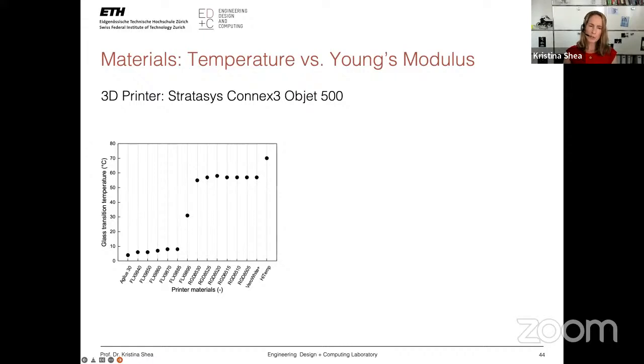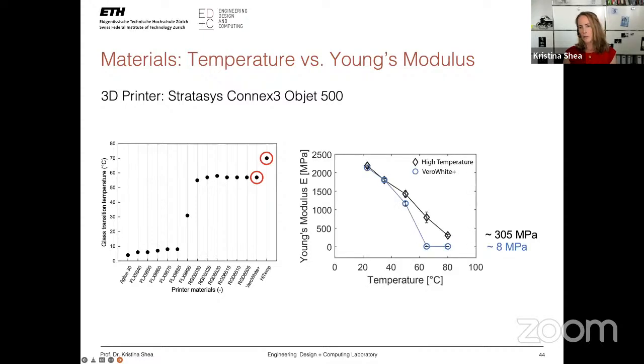And here the principle that we're going to use is a bit different. So here are the materials, same materials I showed you before, and same glass transition temperatures. But now this work was done by Thomas Lumpe in my group. What he did is look at the change of the Young's modulus when you heat up the materials. Before we were looking at the glass transition temperature and the programming of the material. Now the switch is to say, okay, what happens to the Young's modulus and the compliance of the material as you heat the material?